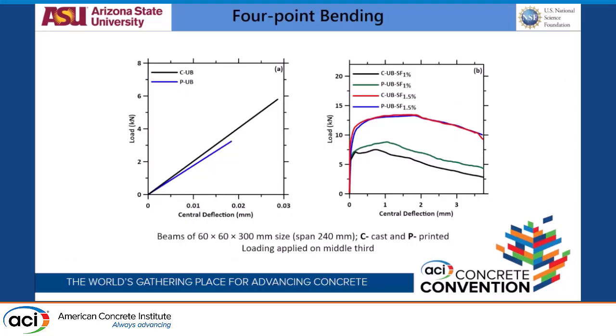On flexure, how do they perform now? In compression, we saw that the cast sample and the printed sample had similar compressive strength, but for the UB mixture shown on the left, we have about a 40 to 50% loss in flexural strength when comparing cast versus print. Everything labeled by C-dash represents the cast samples, and everything labeled by P-dash at the initial represents a printed sample. So we see that there's a significant loss of flexural strength. Why does it happen? These smaller voids that are present in the print, despite the flowability and the rheology being maintained, are still significant when there's a tensile load rather than compression, because under compression they usually have a closing effect, while here they have a stress concentration effect. So that's there.